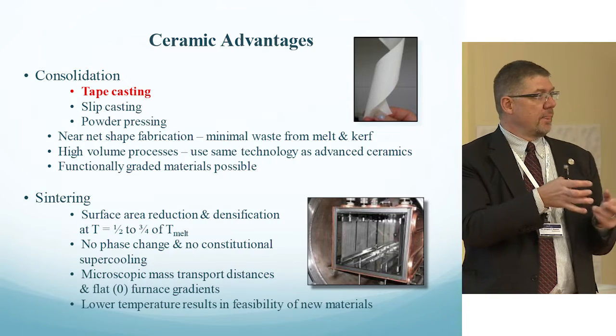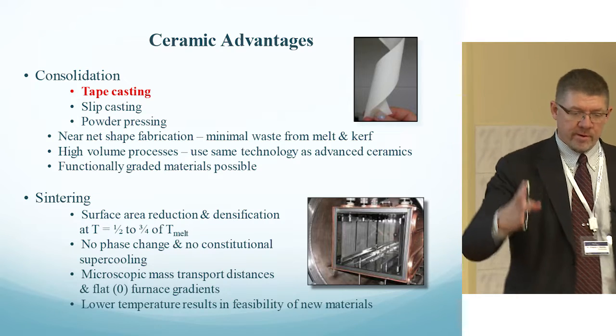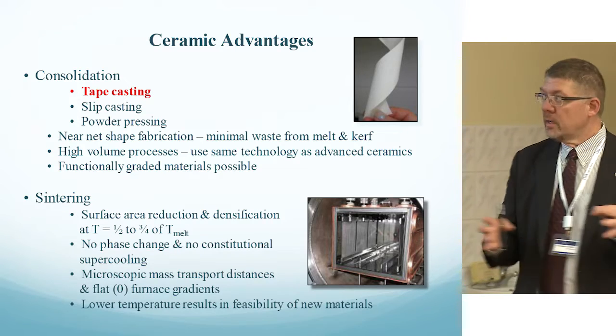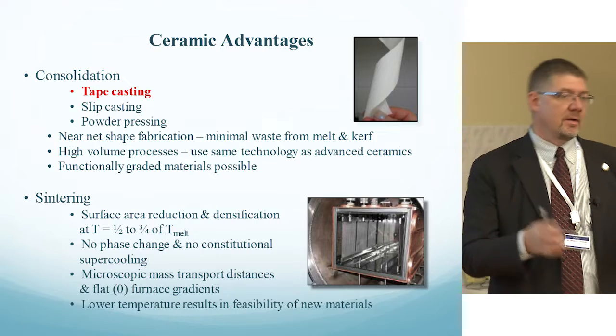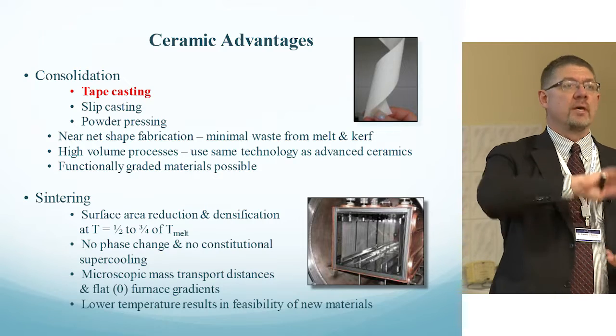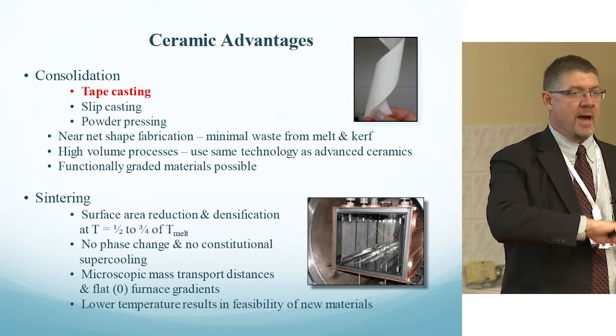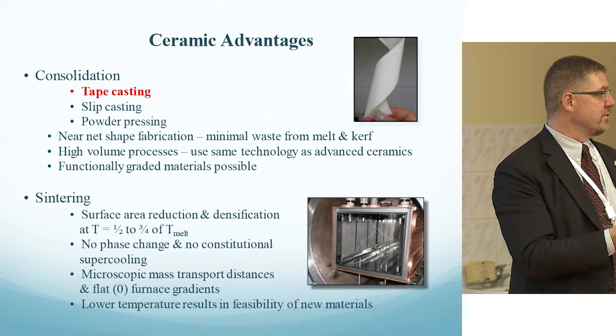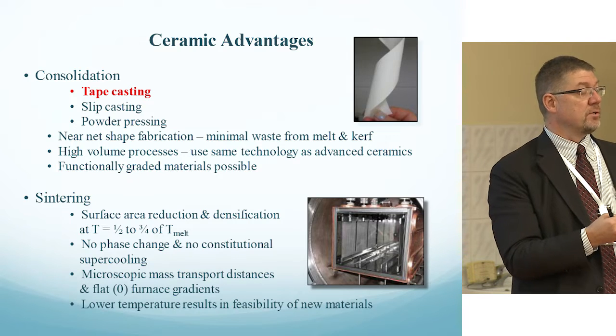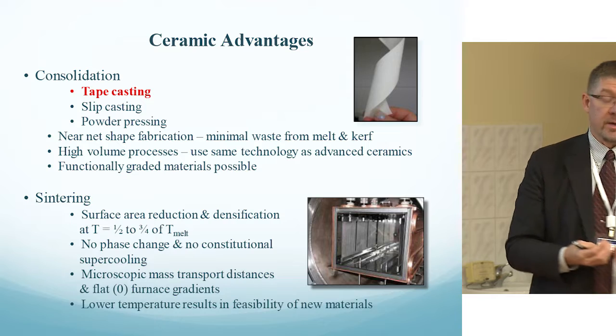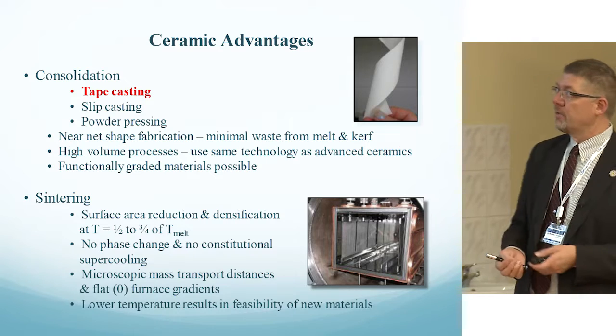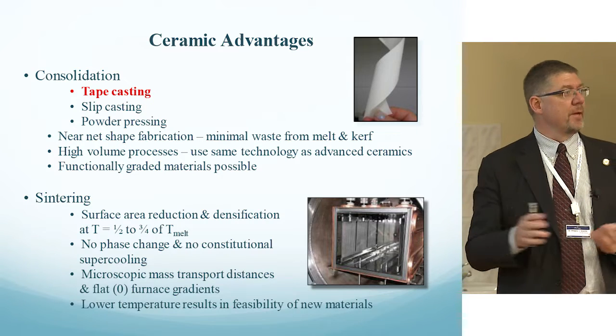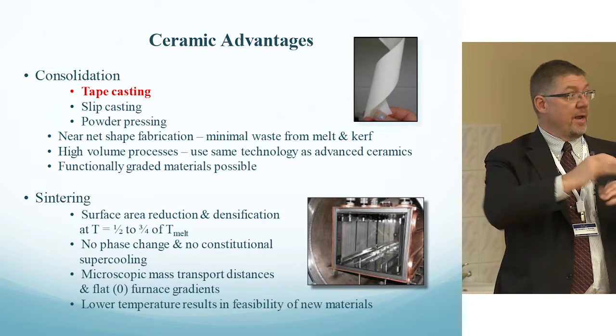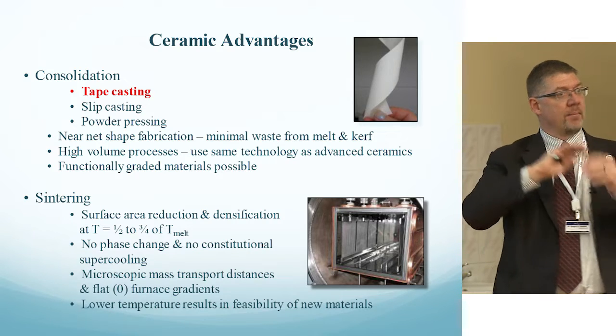dome, if you make that out of sapphire, you're going to grow a very large piece of sapphire, usually with an HEM method. And then you're going to take a fabrication machine and hog that material out, and 90% of it is going to be lost in the fabrication process. And because it's sapphire, it's probably going to take you several months to get it to the right shape. With the ceramics, you can take the powder, press it into that dome, with a press on the top and the bottom, and it comes out.